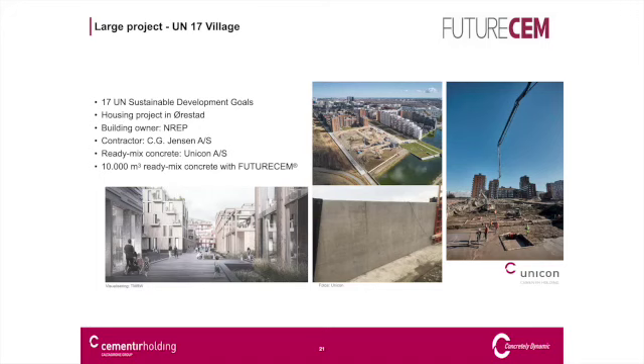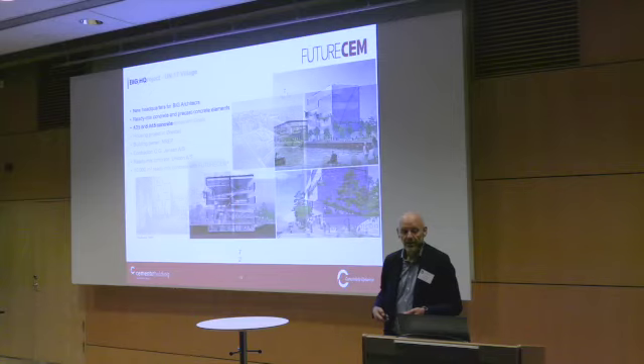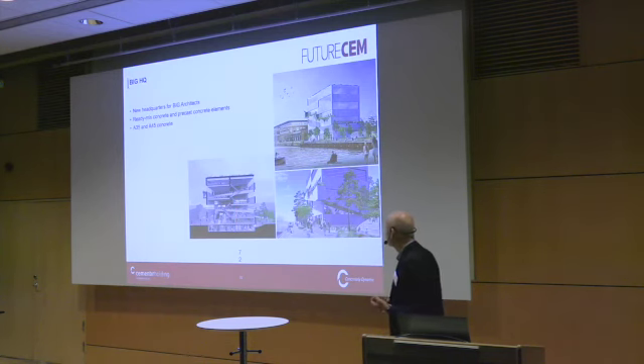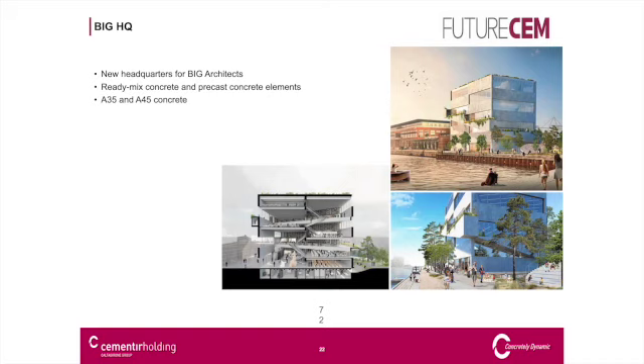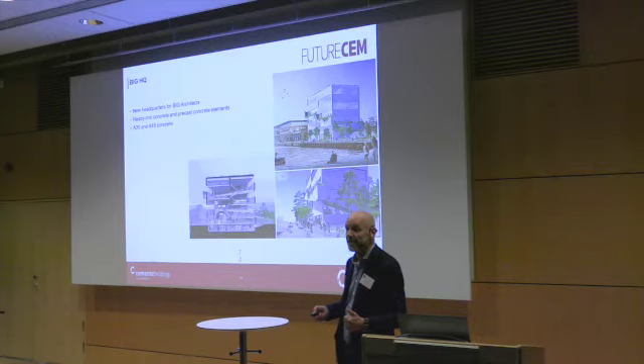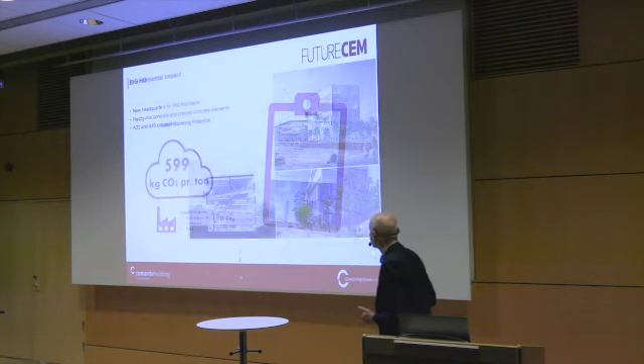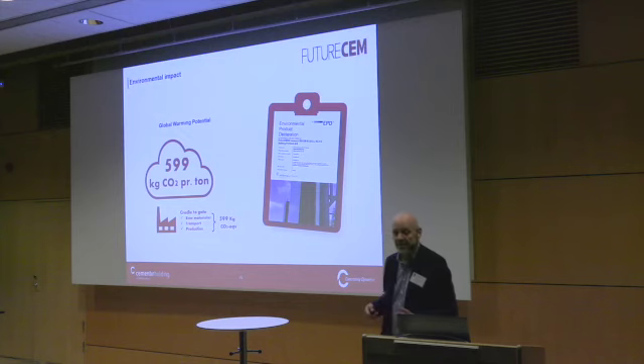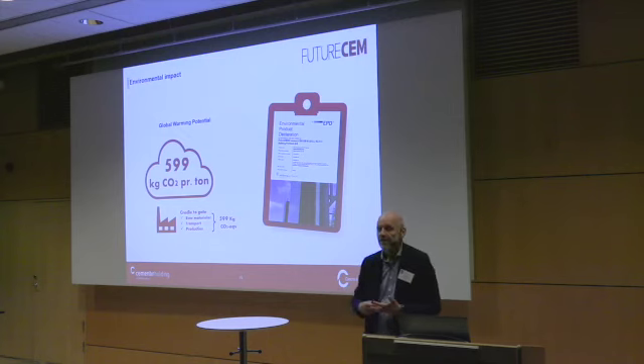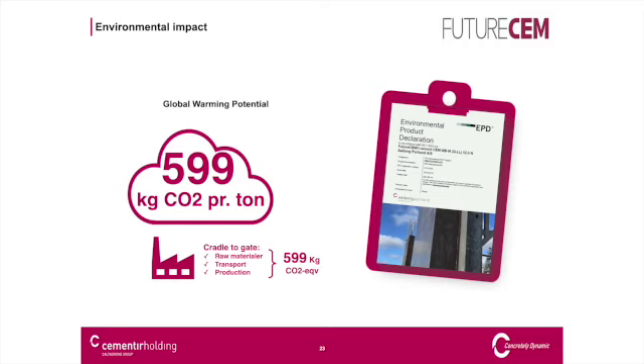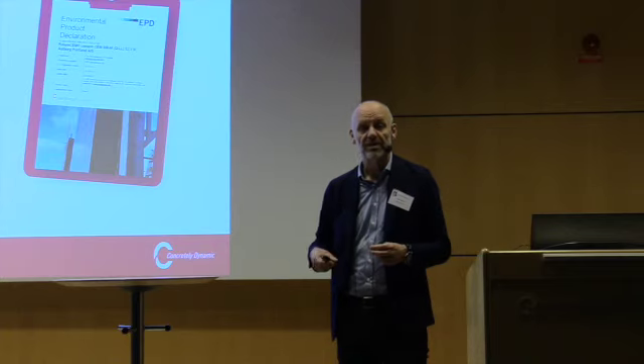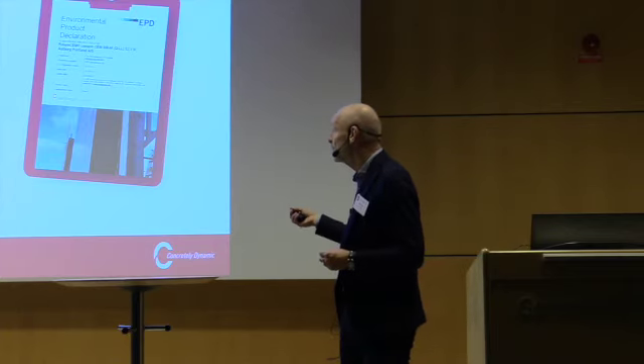It's been used in a number of big constructions already. I would like to mention this because this is the big headquarter, and BIG is a very big architectural firm led by Bjarke Ingels, which is quite well known. They're building a new headquarter, and they wanted this to be 100% green, so they selected FutureCem as their cement type. So this is a good launch. For the environmental impact, the EPD for the FutureCem is a little bit below 600 kilos CO2 per ton of cement. That is equivalent to about 30% reduction compared to the CEM I, which is the main cement type, and this can be used more or less equivalent to that.